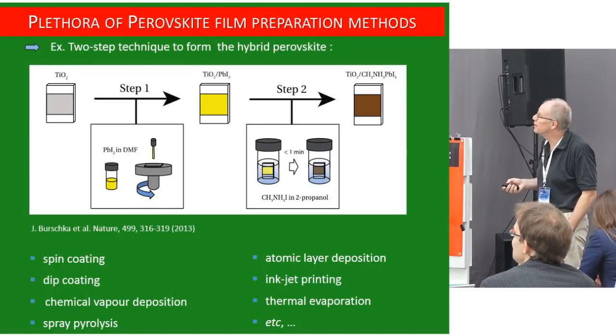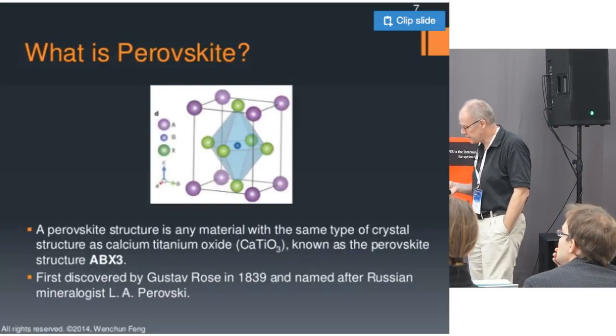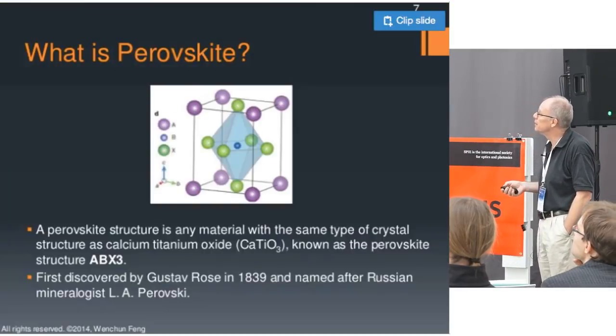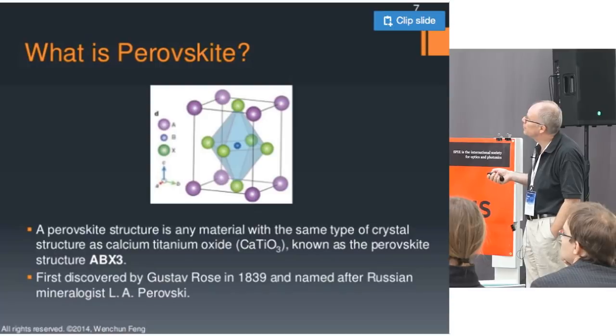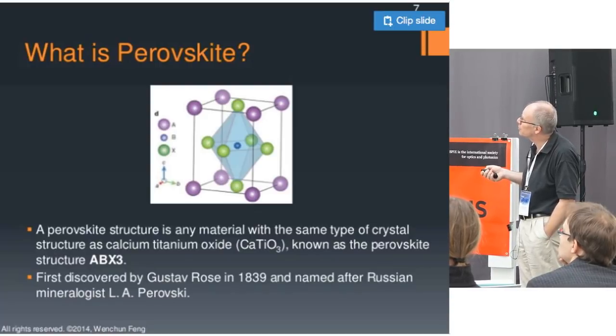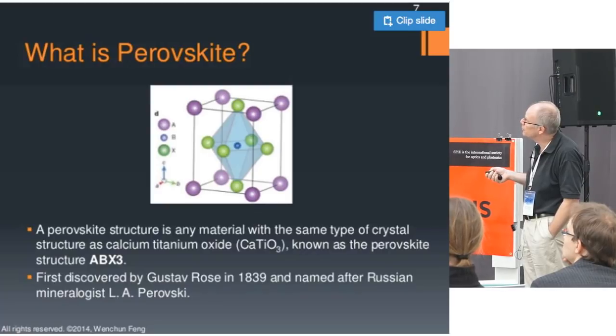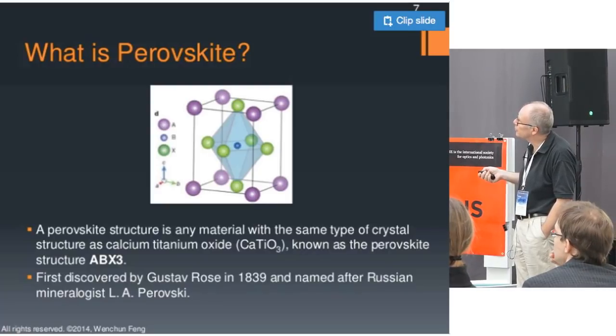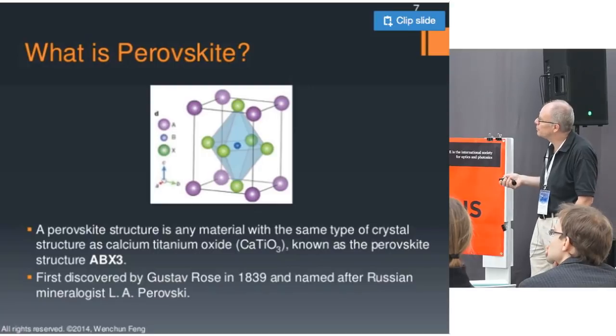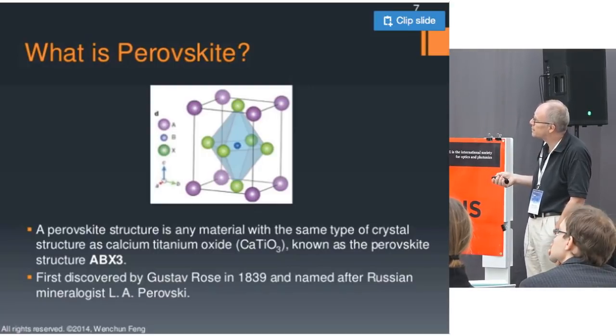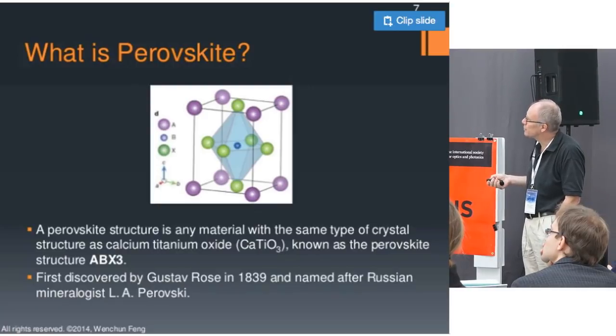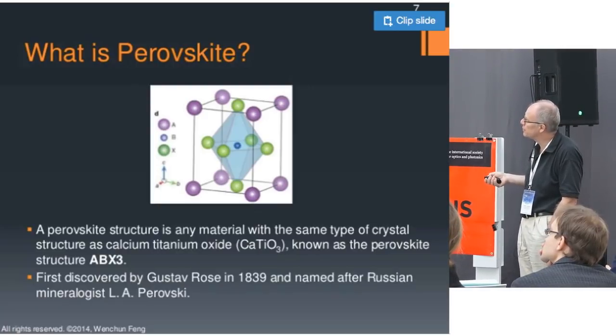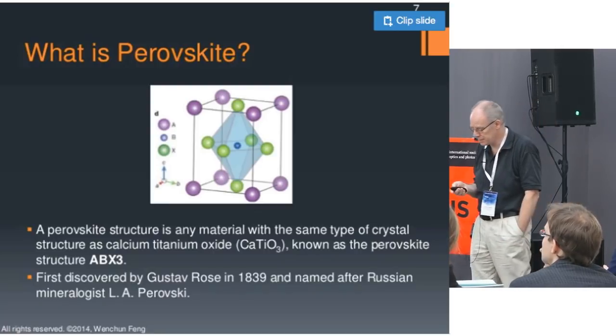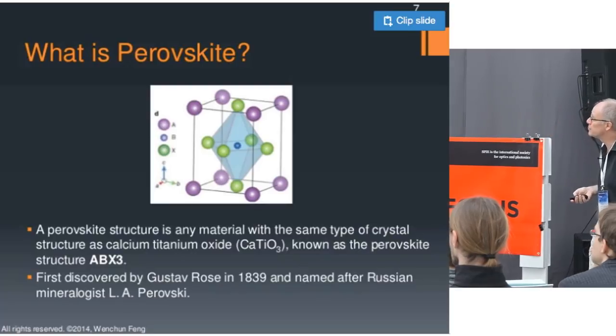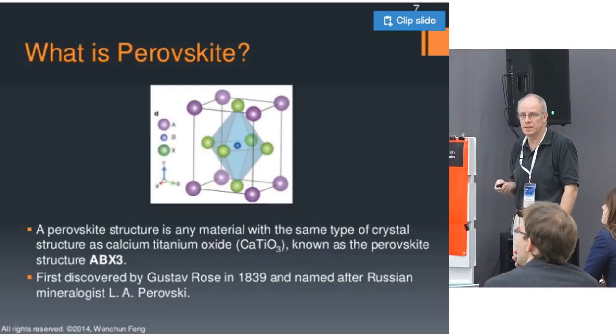Here is what a perovskite is. Well, it's a structure. It's a cubic structure. You have your metal, that's the lead in our case, in the corner of the cube. The cation, our methylammonium, is in the center. And then you have your halide in an octahedron around the lead. So that's the perovskite structure. It was first discovered in calcium titanate, so classical perovskites are oxides. In the 1800s it was discovered by Gustav Rose, and he named it after Perovski, who was a Russian person. So it's a structure, and superconductors, for example, are often based on perovskite structures.